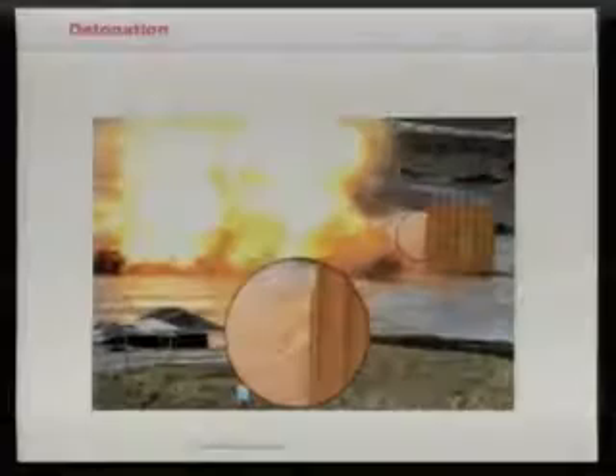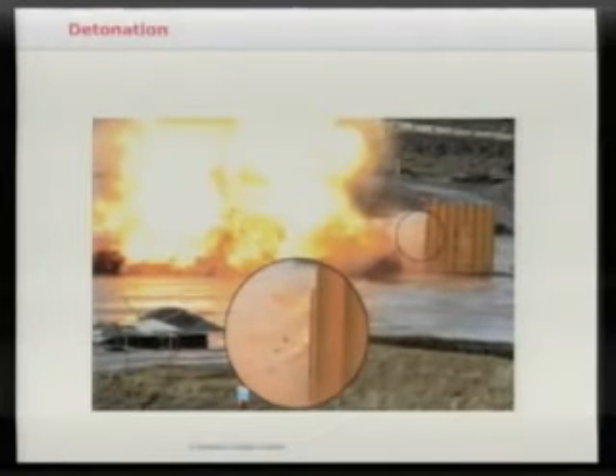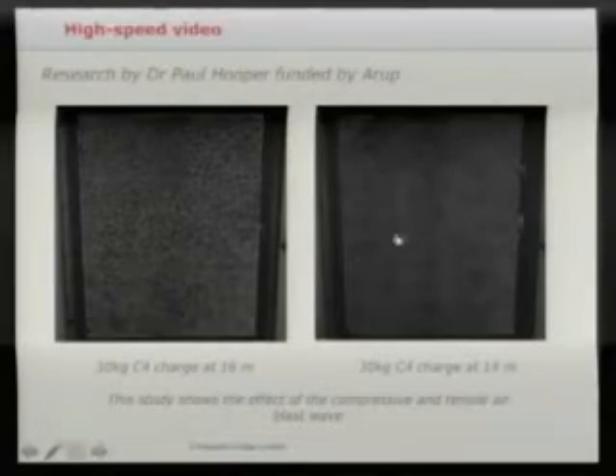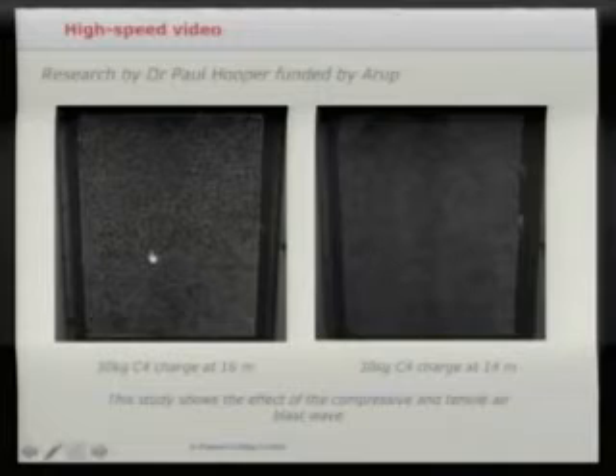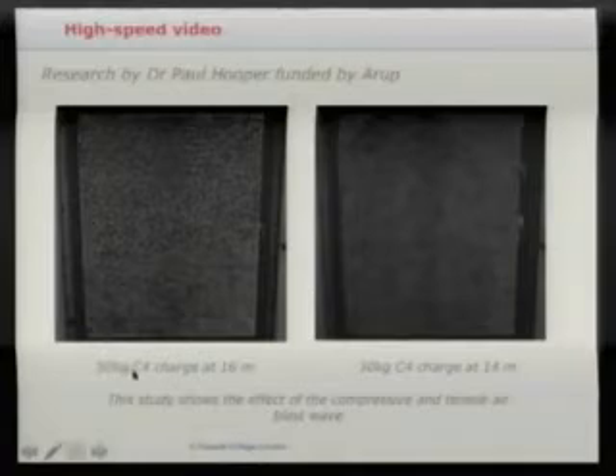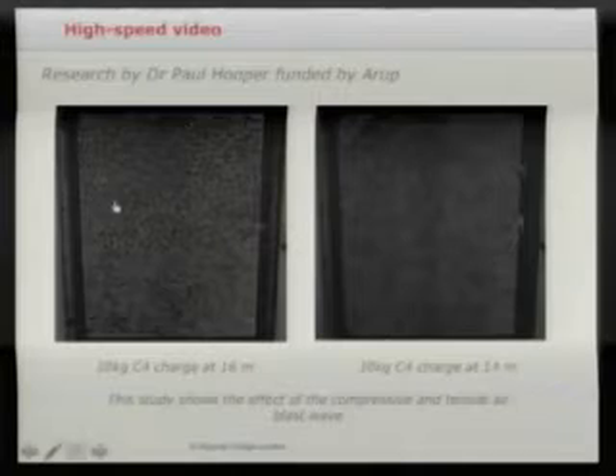So here you can see the blast event going off. And if you look closely there, just ahead of the cubicle, you can see that the laminated glass sheet has been pushed in and then pulled outwards by this blast event. So we do a series of tests at different standoffs. And this shows here two particular cases. This one is 30 kilograms of C4 at 16 meters. And this one is the same charge, but closer in at 14 meters.